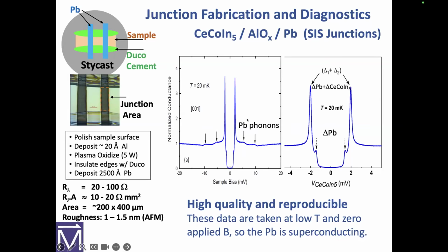So the last one I showed you was aluminum lead. This one is CeCoIn5 lead. And what we have here is the lead. This is really great looking tunneling. But I can't tell you what percent is predominantly single-step elastic tunneling. We're getting a great tunneling density of states. We can see the delta 1 plus delta 2 of the lead and the CeCoIn5.